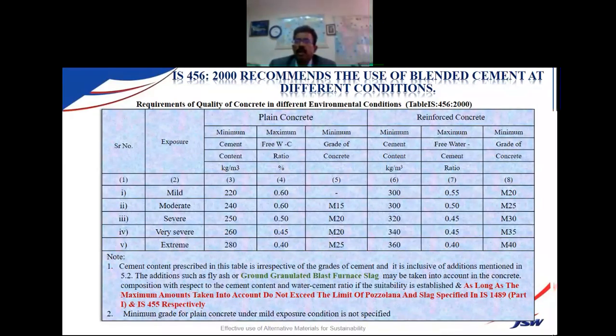You may ask me, sir, is it permitted as per the Indian standard codes? Because we, being civil engineers, follow all the standard codes for steel, cement, and all other materials. Definitely, dear friends, the usage of mineral additives is permitted as per IS 456. You can see this Table 5, it clearly says that you can use additions of fly ash or GGBS to make the concrete, as per the limitations. The limit for fly ash as per IS 1489 is up to 35%. Whereas for slag, IS 455 is the code for making slag cement. Up to 70%, we can replace the clinker content by using slag.